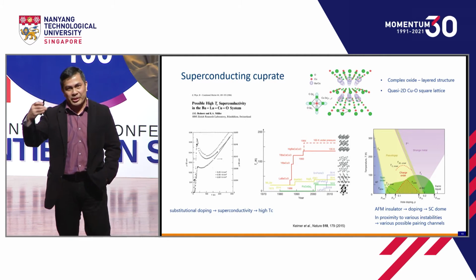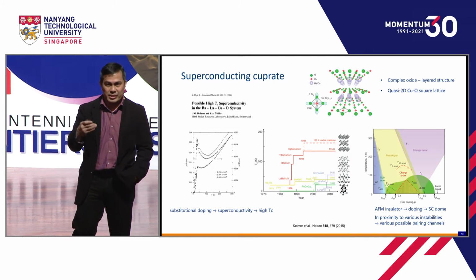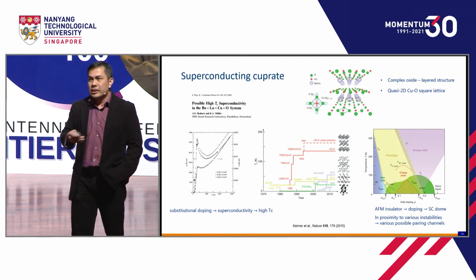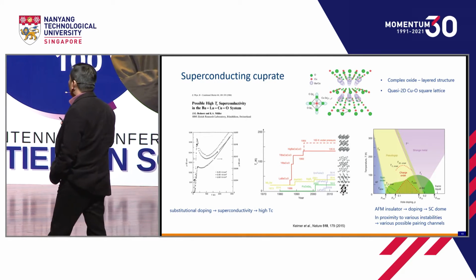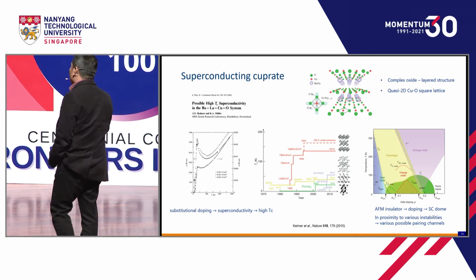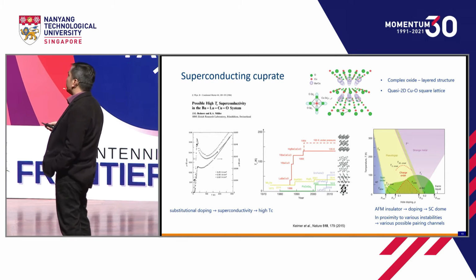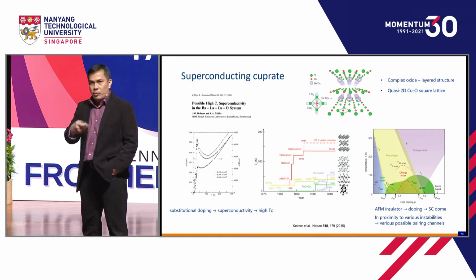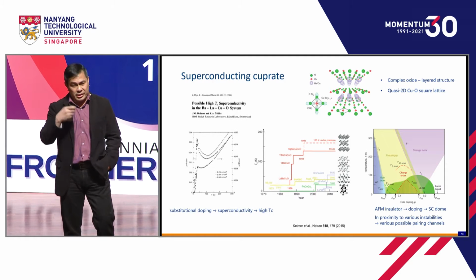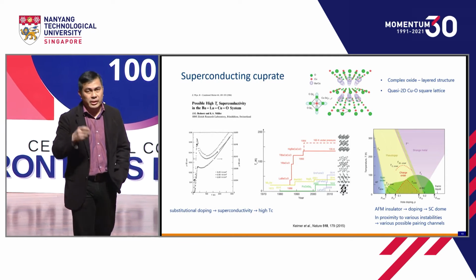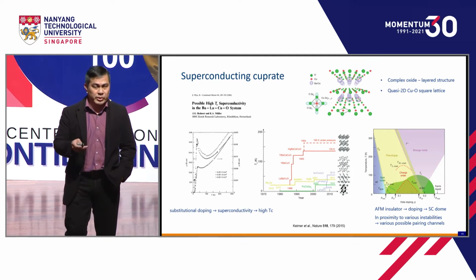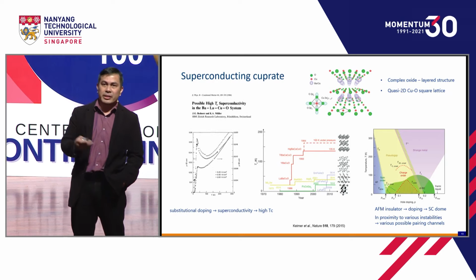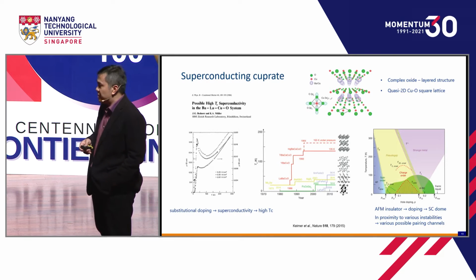Don't think about superconductivity. It's not even a metal. But then, Bednorz and Müller found that when they dope slightly this insulating antiferromagnetic compound, it becomes superconducting with a Tc that is very high. That cannot be explained by the BCS theory.